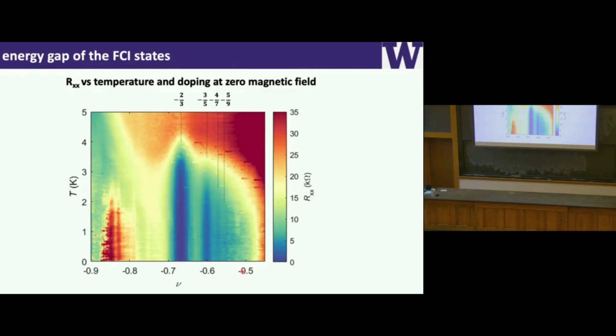The other nice thing about the system, as I mentioned in the beginning, is that it has a large energy gap. What I show you here is a measurement of RxX as a function of temperature. The vertical axis is temperature, horizontal is the filling number. The data is taken focusing on these fractional fillings. The blue color represents the vanishing RxX. Just by looking at this data, you will see that, for example, this -2/3 state, the dip of this RxX can survive to pretty high temperature. When I say high, it's 2 to 3 Kelvin. It's already high if you know about the fractional quantum Hall states. And this data is taken at zero magnetic field. That already tells you the system has a large energy gap. If we do thermal activation measurements, it will tell us the gap itself is about 20 Kelvin.